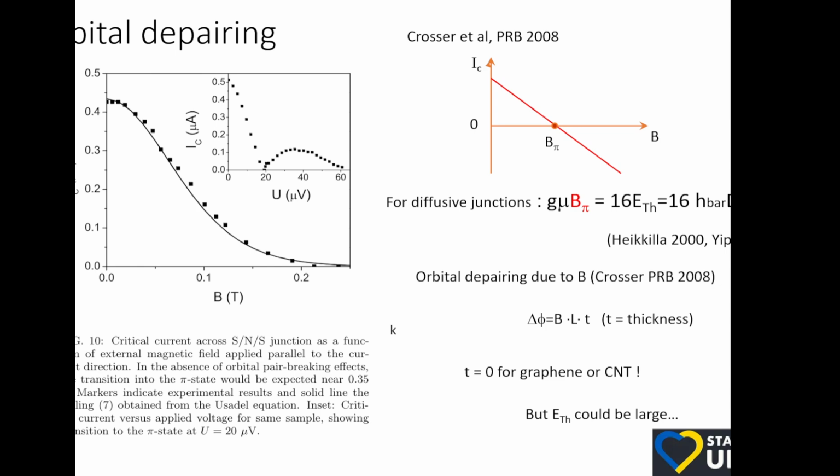That's the energy scale. And then you compare it to Zeeman splitting, because if the energies of the spin up and spin down are bigger, farther spaced than the gap, then you cannot hybridize them into a Cooper pair. There's just no way, right? And that's called the Pauli limit of superconductivity. Superconductivity must be destroyed if Zeeman splitting exceeds the gap.